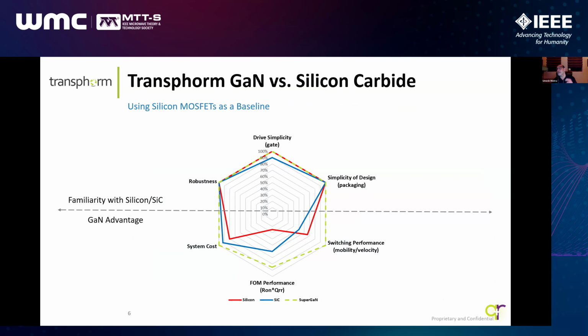Gallium nitride versus silicon carbide. This is for power conversion. A similar metric applies for RF, and that's why silicon carbide lost to gallium nitride, and gallium nitride and silicon are now in the fight for RF solution. So the reason why gallium nitride works is that it has a GaN advantage, and it has familiarity with people who use silicon. So if you look at the spider chart here,